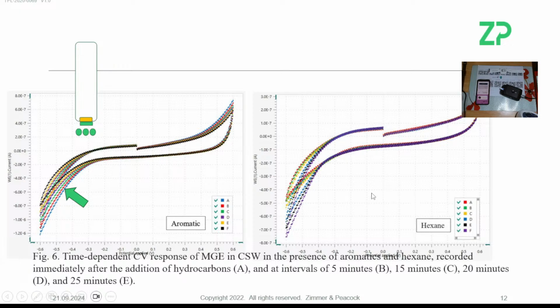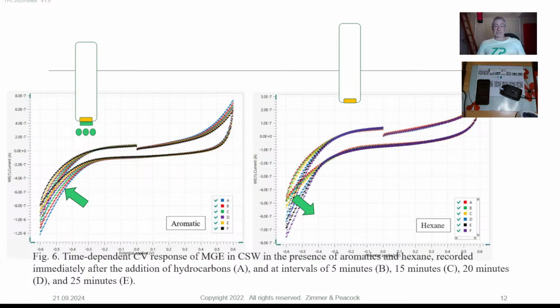Because this is the modified electrode, your hexane signal is increasing, and I think what's happening is you're dissolving away your modified material, exposing more and more of your gold electrode, and increasing your oxygen reduction because of that. So a lot of your signal is due to oxygen reduction, and hexane dissolves away your surface and the oxygen reduction increases. In the presence of aromatic compounds, the aromatic compounds may also be dissolving that polymer, but I think they're actually absorbing onto the surface, so you get the opposite phenomenon. So just FYI, I think that's really what's happening in your voltammetry.